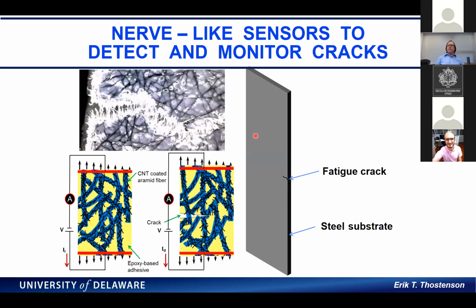So our idea was that we could take our nerve-like sensors. This top picture is a sensor that has carbon nanotubes deposited onto the fibers. You can see the fibers are dark; that is the carbon nanotube coating. This is bonded onto a steel substrate that has a fatigue crack in it. As that crack has grown, the sensor also fragments, because we've designed the sensor to fragment. As we measure the electrical properties and the fatigue crack grows, just like on a different scale where we look at microcracking in the composite, here we're looking at cracking in the steel plate. We're severing those conducting pathways.